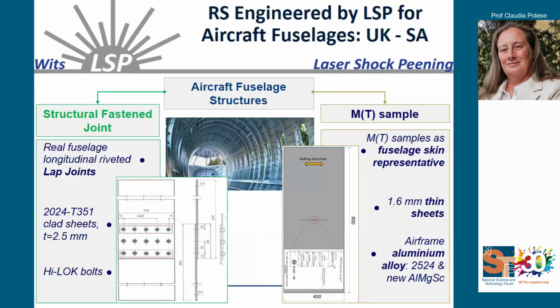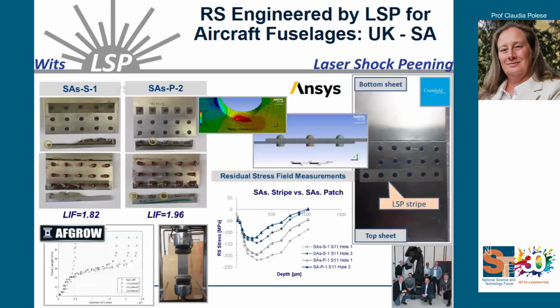Then we talked about and pitched the idea to other colleagues here in the UK. We spoke with the guys at Cranfield, and together with the colleagues from Airbus, we moved this idea to a real fuselage joint, the traditional lap joint, which is the point where the majority of cracks start. So we applied the South African laser shock peening in different configurations. In this specific case, we saw a performance improvement of basically 2 times. That means, again, if a crack is there and starts, it will still take basically double the time. So there is much more possibility for the technical team to identify and correct the issues.